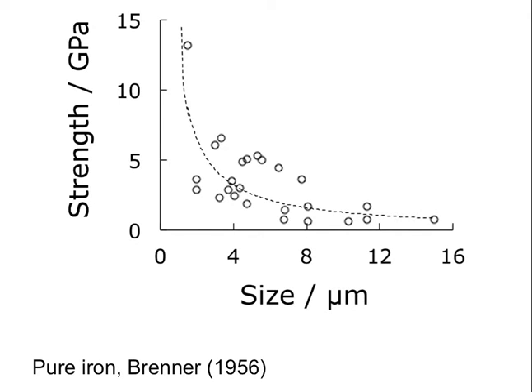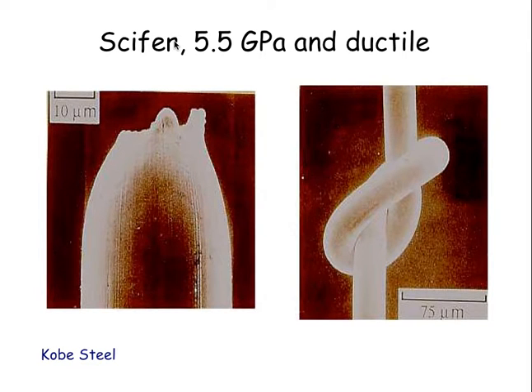Back in 1956, we could make iron on the order of 14 gigapascals strong. It's a single crystal and tiny, so the probability of finding defects is very low. The strength approaches its ideal strength of about 21 gigapascals. But as we scale up, the strength collapses to normal levels because defects arise. We can't rely on perfection to get strength.